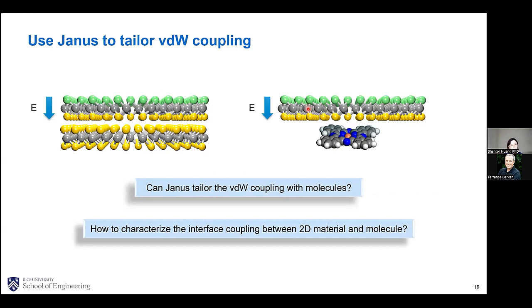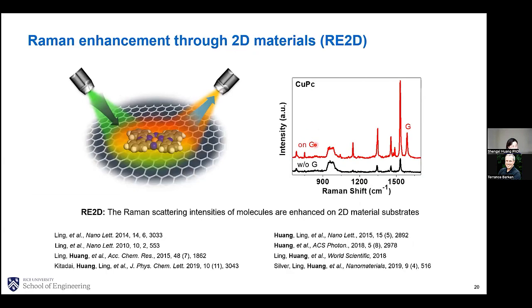But now we can use another type of Raman modes, the high-frequency Raman modes, and actually the Raman modes from the molecule itself. Because several years ago, a phenomenon was discovered called Raman enhancement on 2D materials. Basically, if you put some organic molecules on the surface of a 2D material, you can see the Raman modes of those molecules enhanced. Here is an example of a molecule called copper phthalocyanine, or CuPc.